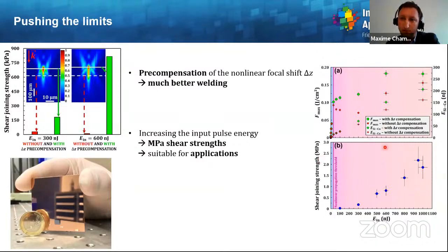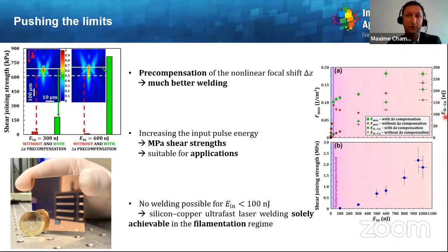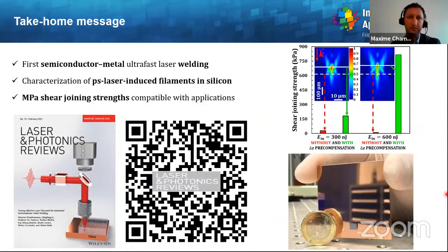And the reason is that when you precompensate the nonlinear focal shift, you increase the maximum fluence at the interface, as well as the energy deposited at this interface. I mean, the energy reaching the interface, sorry. Then we observed, noteworthy, here in purple is the nonlinear propagation threshold, and one can see that no welding is possible between silicon and copper for input pulse energies below 100 nanojoules, meaning that silicon to copper ultrafast laser welding is solely achievable in the filamentation regime. So if you want to do this, you have to take into account the nonlinear focal shift and the filamentation. So here is the take-home message.